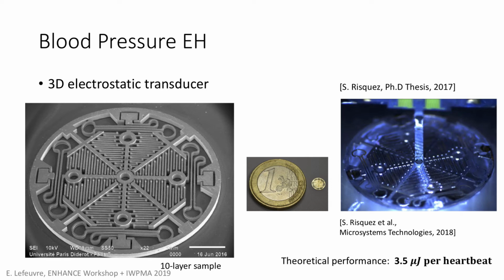Okay. So that's a photograph of the device. It's 5 millimeters in diameter, and here you have a test of the springs to check that after thousands of 1 millimeter displacement, there was no problem. Actually, we were not patient enough to break it, but it never broke. That's a good point with metal compared to other materials we can discuss, but it's very robust, I'd say.